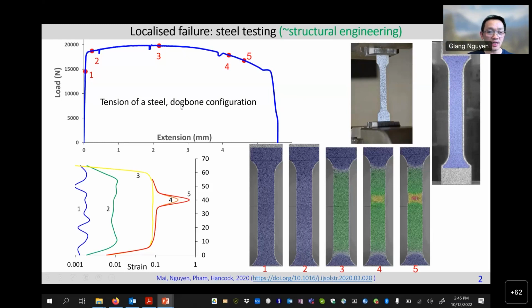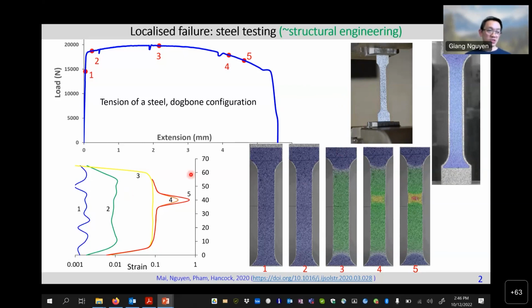So if we plot the strain distribution at different stages of loading from 1 to 5 here, we see something very clear. Before point 3, you can see here, the deformation looks really homogeneous. So it's almost the same everywhere. But beyond it, we would see something very localized. That's the red zone here that in the end fractures. Okay. And if we plot the strain distribution along the vertical line, you can see at 1 it's relatively all right, not much fluctuation because of the intrinsic inhomogeneity of the material. 2, 3 is roughly similar, but beyond 3, roughly the peak, we see one zone in the middle starts to develop very intense strain.